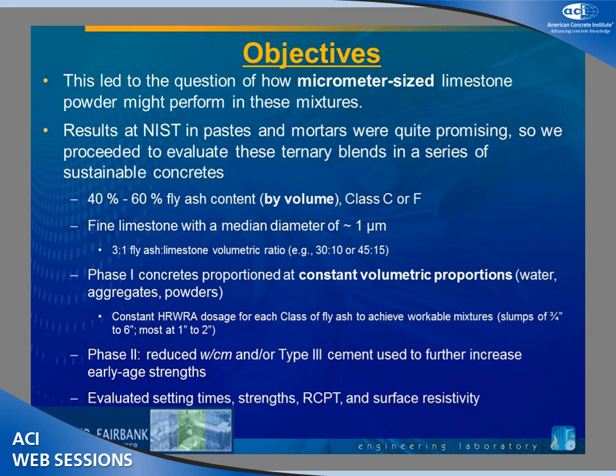We have two levels of cement replacement. Either 40 or 60% of the cement is being taken out of the mix by volume. I'll get to a little bit more why we're doing it by volume. We have both a Class C and a Class F fly ash that we're doing this with.